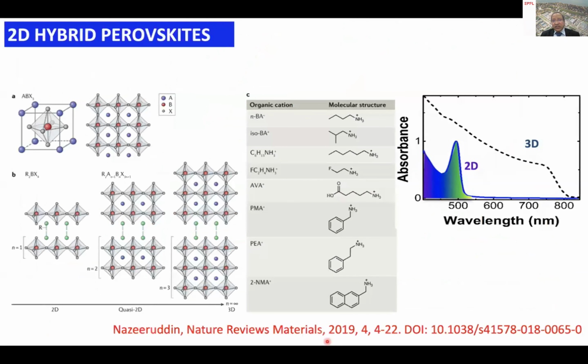Now I come to the interface engineering. So far I have discussed the three-dimensional perovskites. But if we change the cation size from a small size to larger cations, which I have given some examples of here, then you form a two-dimensional perovskite. The difference between the two-dimensional perovskite and three-dimensional perovskite is contrasted here, the visible spectra. The visible spectra clearly shows the 3D absorption spectra going up to 820 nanometers, whereas the 2D perovskites have a spectra only between 400 to 500 nanometers. However, the stability of the two-dimensional perovskite is significantly enhanced compared to the three-dimensional perovskite.